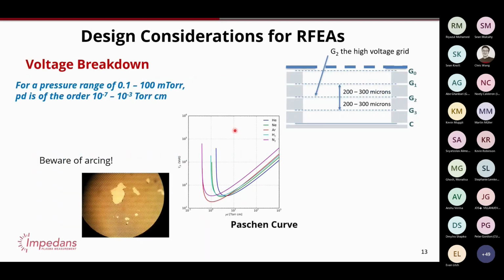What else must we consider? As I mentioned, we need to make these distances very, very small. But the problem is, depending on the gases that are present, you want to avoid getting arcing in here, because if you want to measure ions at 1000 eV, 2000 eV, you have to apply very large voltages on this grid with respect to the other one. So you don't want to get breakdown happening inside here. So you can work out what's needed here.